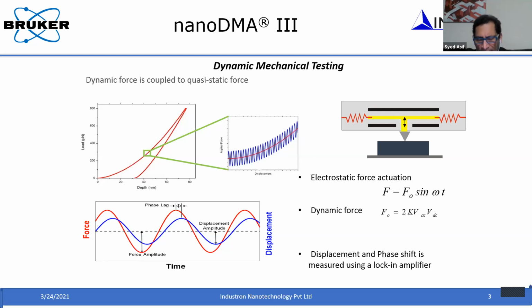So typically in an experiment, we apply an oscillatory force of known amplitude and measure the displacement amplitude, and also measure the phase shift between this force amplitude and the displacement amplitude.